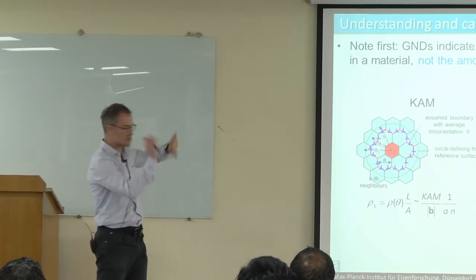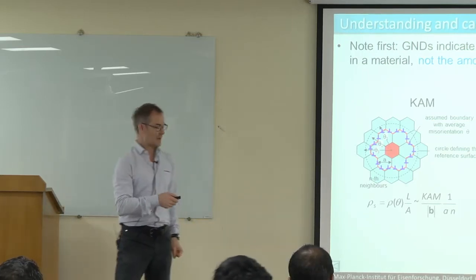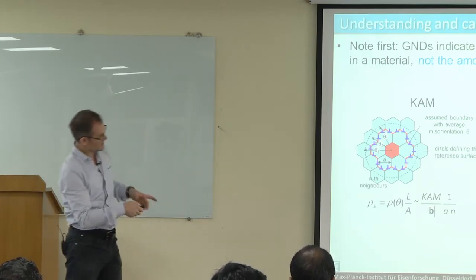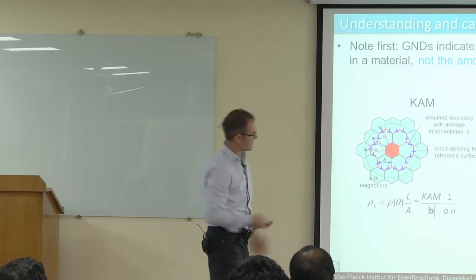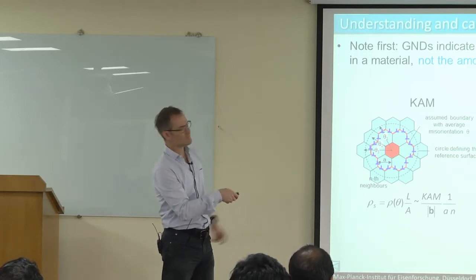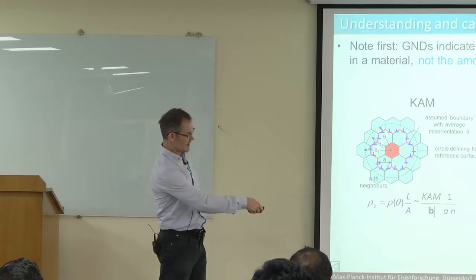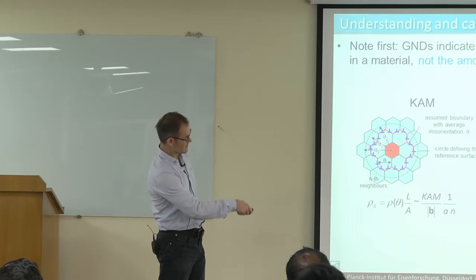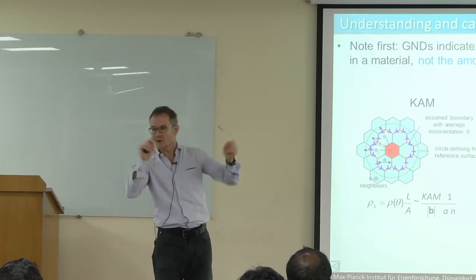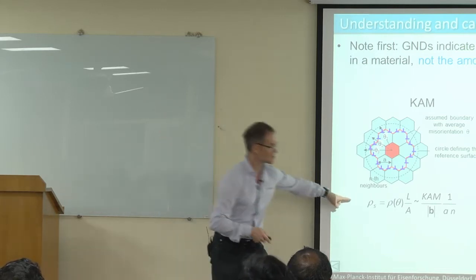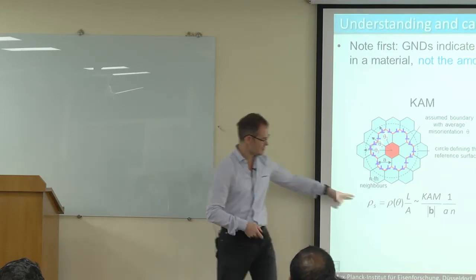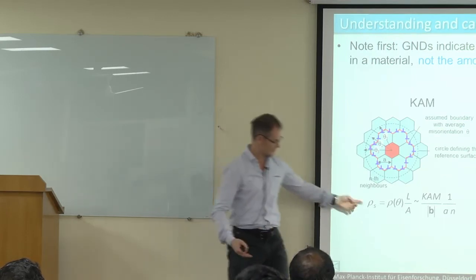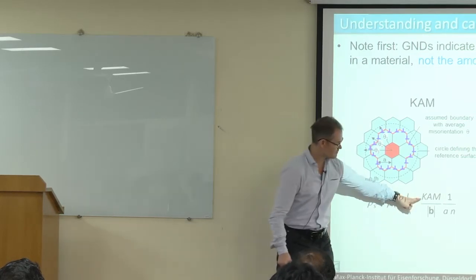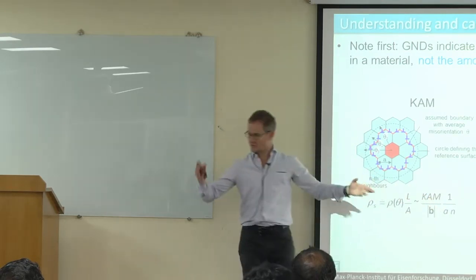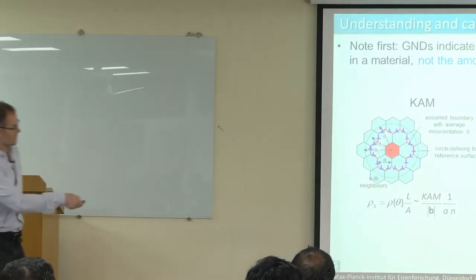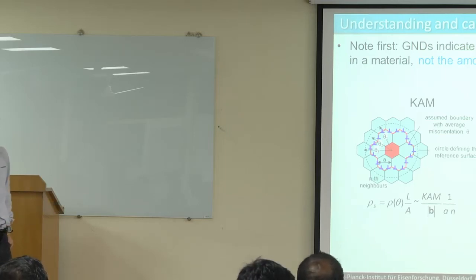And in this way, and here's the equation, it's very simple. And then what can I do? I can make an EBSD map, a very large EBSD map, and very large or very small, whatever you like. This is a large one, and now I calculate first the KAM. The software does this automatically. So I plot here my KAM value from 0 to 4 degree. Colors mean blue means no misorientation, and red means 4 degree local misorientation. And now I'm just taking this equation, and I'm changing the KAM meaning into dislocation density meaning. So it's just linear. The dislocation density is directly proportional to KAM. So the rest is just factors from the measurement. And that means I can, instead of plotting this in form of KAM, plot it in terms of GNDs.